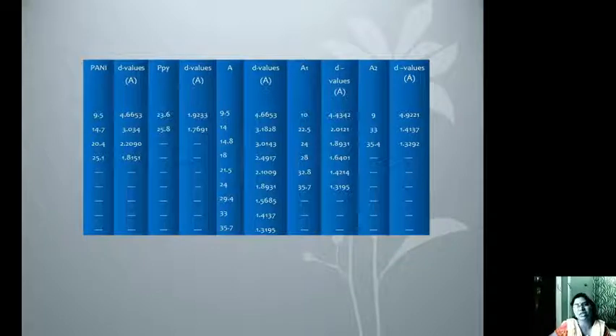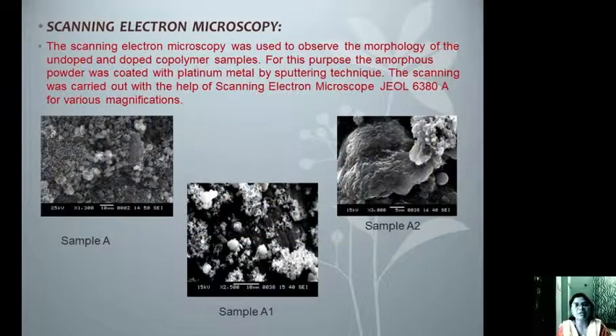the doped ones. The comparison of the two theta peaks shows that these copolymer units are getting aligned in such a fashion that some new crystalline structure is getting created within the sample, because of which the glancing angles are changed and as a result the peaks are altered. Further,